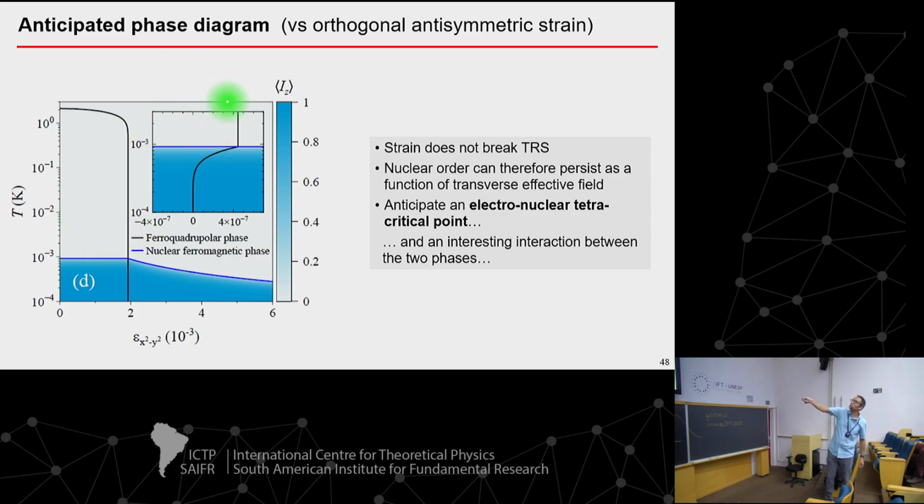So if I zoom into this point, the ferroquadrupole order comes down. Here's the electronuclear ferromagnetic order. And the reason that this backbends is, as you cool down into the dipolar ordered state, I've co-opted some amount of the quadrupole. The pseudospin has rotated a little bit. So now it requires less of the transverse field to suppress the quadrupole order. And in fact, the temperature dependence you see here is just from the growing order parameter associated with that. That's a kind of funky phase diagram as well.